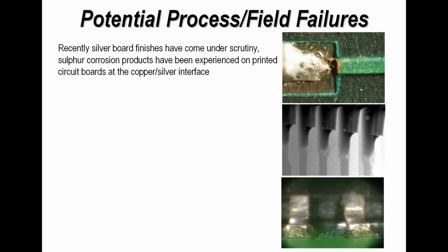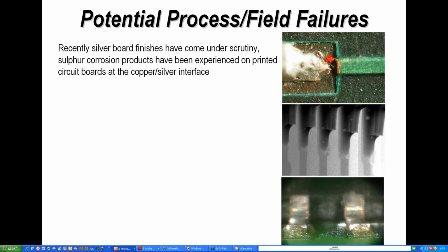And what I illustrate in the photographs here in this area, corrosion has taken place and actually eaten through the track and pad interface. The X-rays below it also show the same thing, and you can see what appears to be mouse bites in the surface of the copper, and in time these would go all the way through. In the bottom photograph you can see corrosion products actually starting to span between two pads and two terminations on an SOIC. And this is to do with sulfur in combination with silver and copper surfaces.